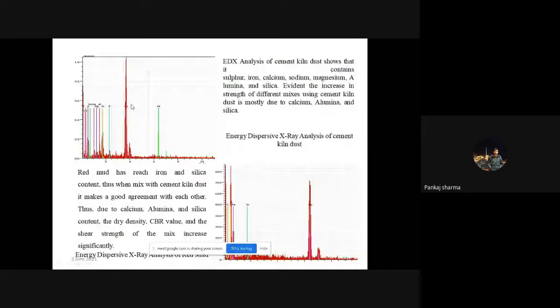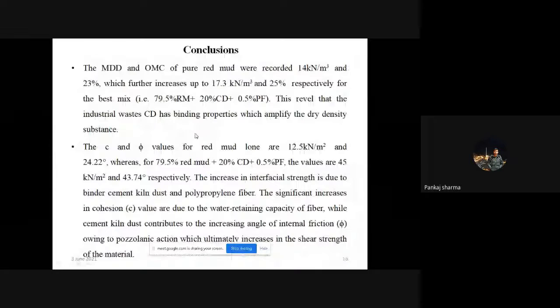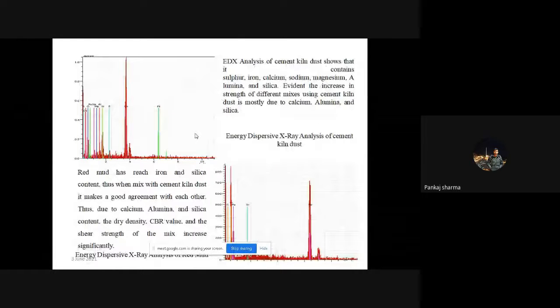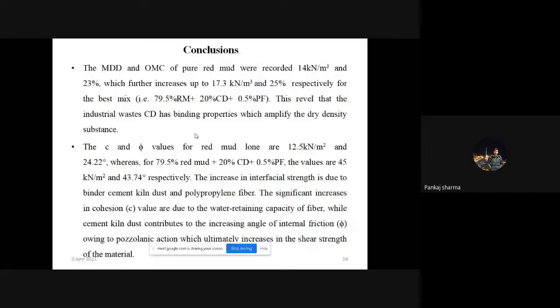It contains predominant amount of calcium and silica. From both figures, it is clear that it contains calcium, silica, alumina, which increase the shear strength of the mix. Hence, from the conclusion, the red mud maximum dry density and optimum moisture content was recorded 14 kilonewton per meter cube and 23%, which is further increased up to 17.3 kilonewton per meter cube at 25% of moisture content. Hence, the 79.5% of red mud and 20% of cement dust with 0.5% fiber is recorded as optimum. Also, the shear strength parameter was found maximum for this mix.